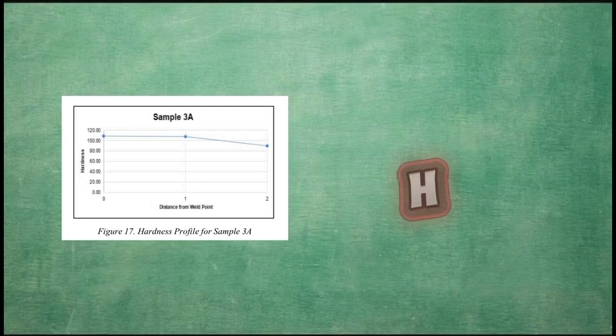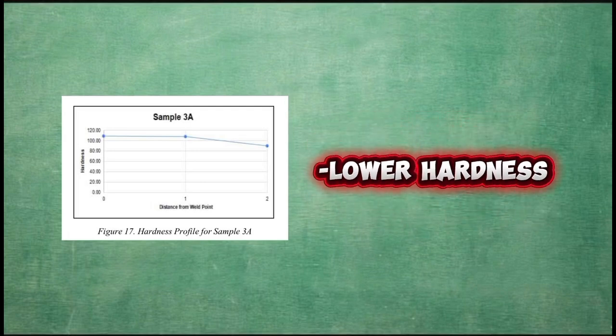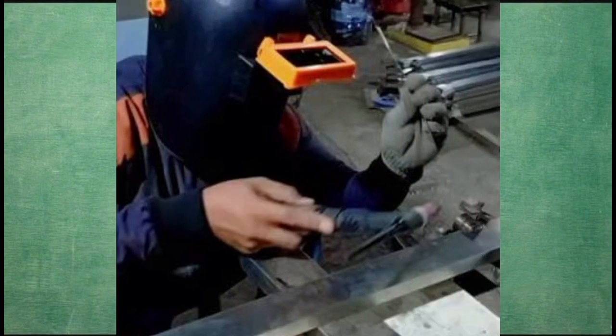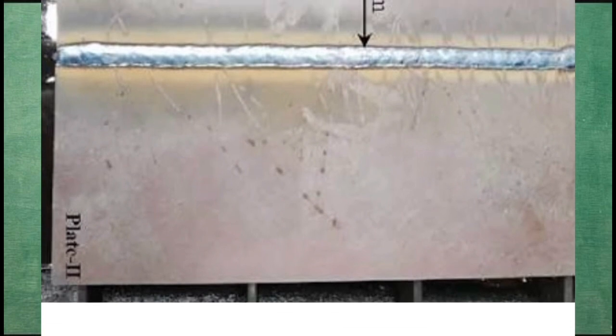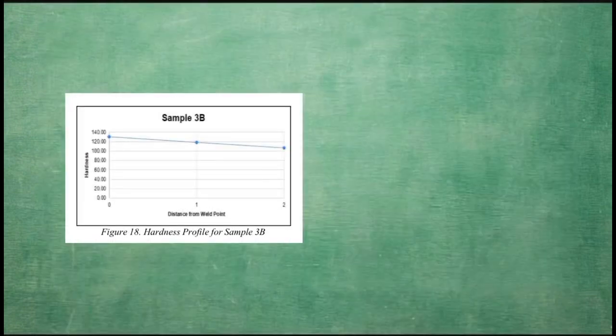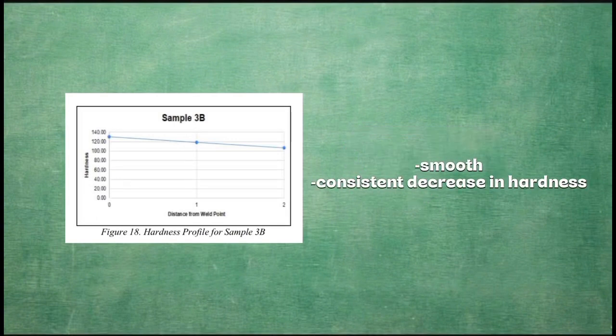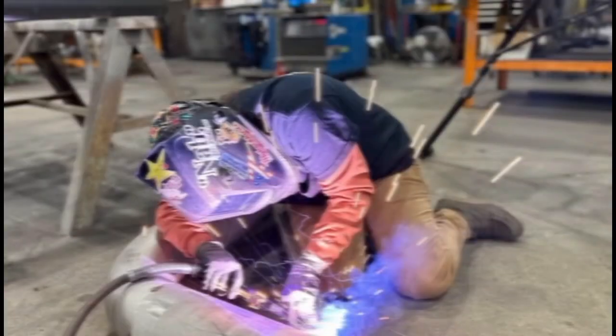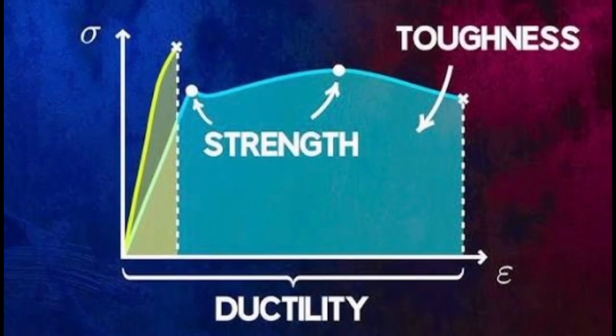Sample 3A, tempered, displayed lower hardness values compared to the quenched samples because tempering reduced brittleness and relieved internal stresses. The gradual decrease in hardness indicates a more balanced and stable microstructure throughout the heat-affected zone. Sample 3B, tempered, showed a smooth and consistent decrease in hardness with distance, indicating controlled thermal behavior after tempering. Although tempered, it maintained relatively high hardness, suggesting a good balance between strength and ductility.